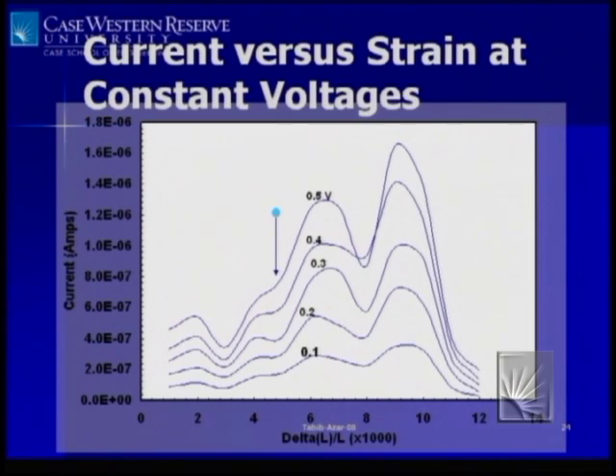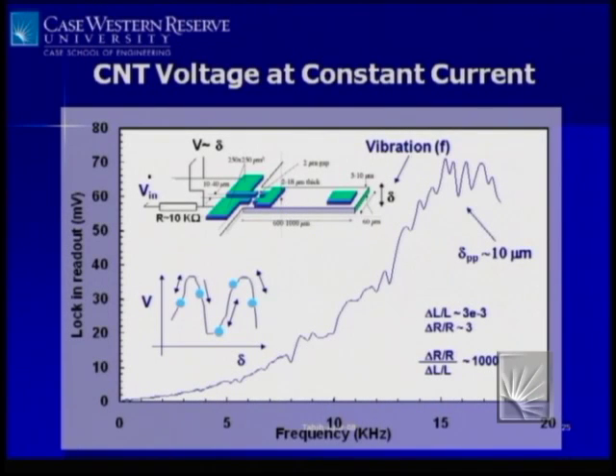These are due to carbon atoms in different layers of the multi-wall carbon nanotube grinding against each other. They go over each other, and then they're in their troughs and so forth. There is a modulation, and there is also an overall change, which is explained by Andrews et al. It's a 1 over R dependence of the effects that we see in the electromagnetic regime. You can also do dynamic measurements by vibrating this and trying to detect the vibration spectrum of the cantilever beam by looking at the piezoresistive signal.